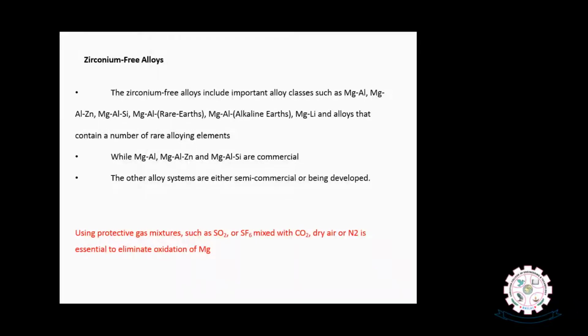In zirconium-free alloys, basically some other alloys like magnesium-aluminum-zinc, magnesium-aluminum-silicon, magnesium-aluminum-rare earths, magnesium-aluminum-alkaline earths, and magnesium-lithium based alloys can be found in this group, while magnesium-aluminum-zinc and magnesium-aluminum-silicon are the commercially available magnesium alloys which can be found outside from different vendors. The other alloy systems are usually tailor-made and semi-commercial, and sometimes they are developed specifically for a few applications by individual research groups.